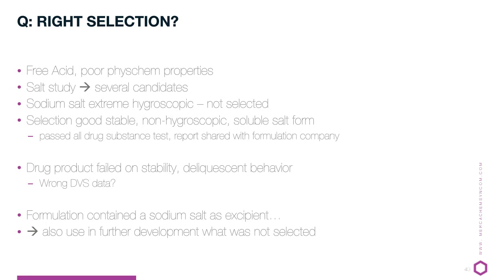Second example of did we do the right selection? In this case we had a free acid, only very poor physchem properties. Salt study was done, there were several candidates, and in the end a sodium salt was obtained. Being a sodium salt and the preferred one to take, that was tested, but it shows to be extremely hygroscopic, so it was not selected as the preferred candidate.